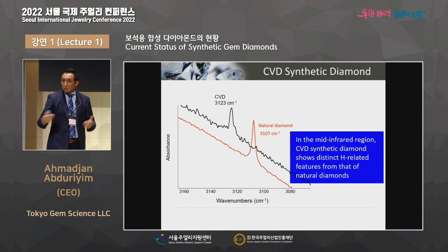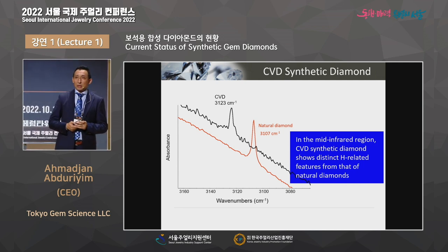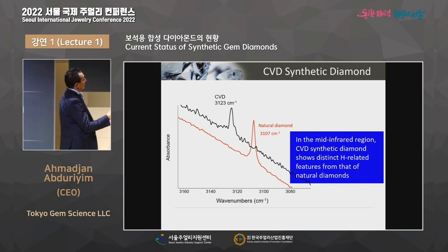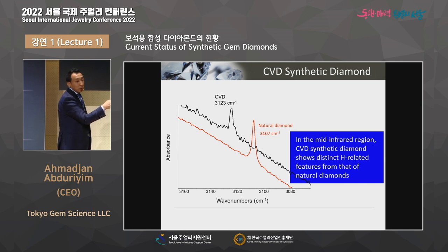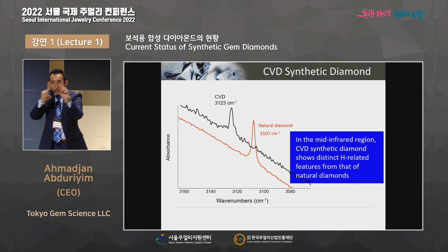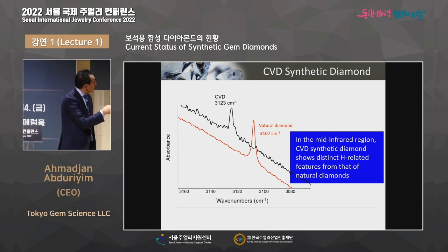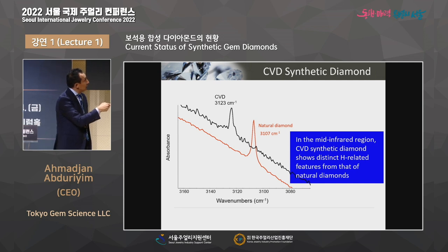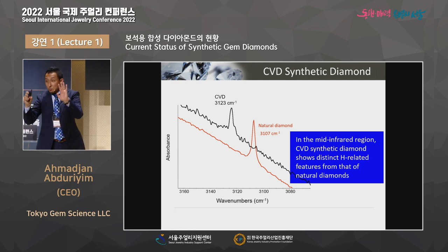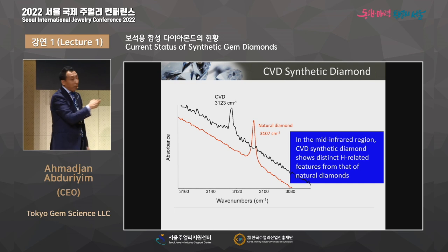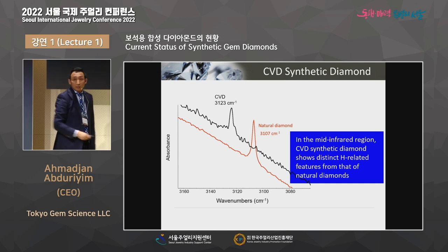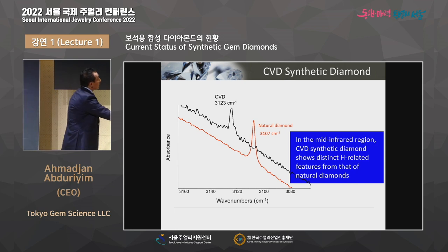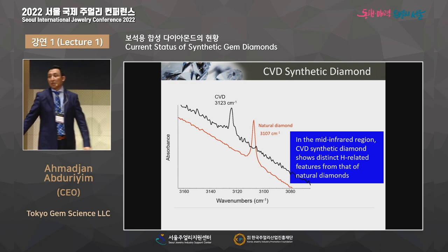And in the lab, of course, we use a lot of optical instruments. You see, this is FTIR, the infrared range. CVD diamond shows hydrogen, at 3,123 wave numbers in this area. Natural diamond, 3,107. This is very important to tell the difference. It's very close, but it's different. Natural diamond never shows this one, and the CVD diamond never shows this. But after the CVD diamond is treated by high pressure, high temperature, this will disappear and show the same structure as natural diamond. It shows this same peak as well.